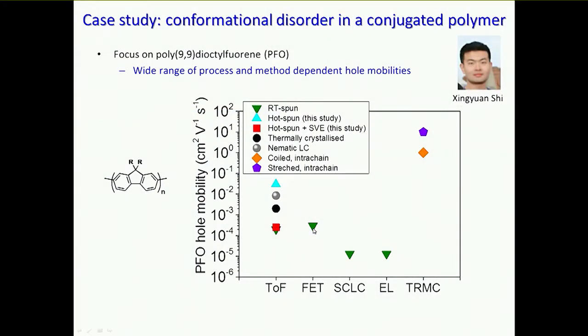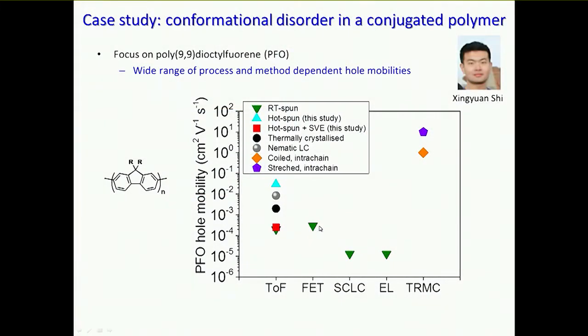this is something that it's not easy to make an FET with PFO, because you have to get an electrode that will talk to the minus 5.8 HOMO energy of the polymer. So getting a suitable contact is not that trivial. We have done it, but we need to be absolutely certain that we are working with a perfectly glassy film. So this number is from the literature. It's not our number. And from the literature, it's quite likely that if people were not aware of the possibility that beta phase could be introduced during processing, that beta phase could be there and could be dominating the response. So this number, I cannot say whether beta phase is present or absent, but if it's present, it would explain why that number is not higher.